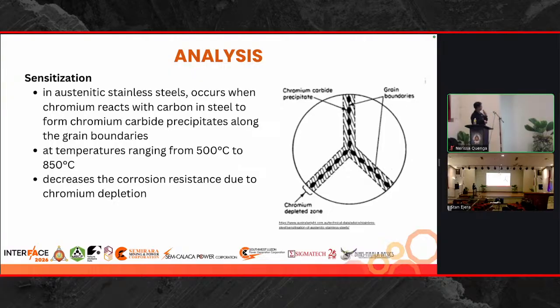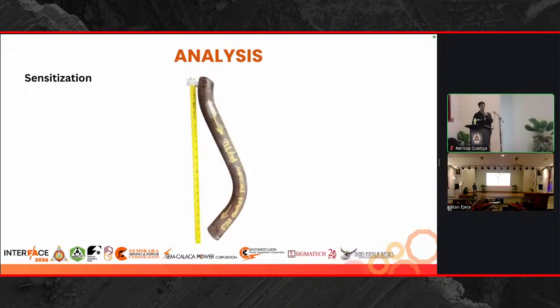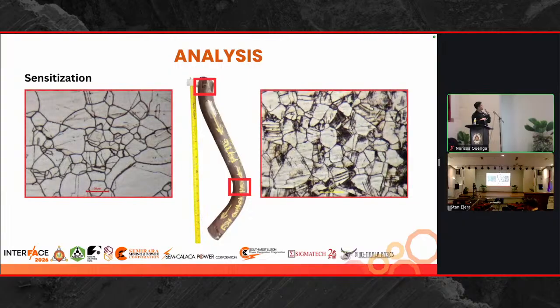Okay, shown here is a sample that was given to us for in-house laboratory testing. This is a stainless steel sample, and we have taken the microstructures from two different parts, one at the top part and one at the bent part. As you can see here, the grain boundaries are coarser than usual. I have annotated the features. This shows that this particular component experienced sensitization, so it has generally lower corrosion resistance compared to its original form.